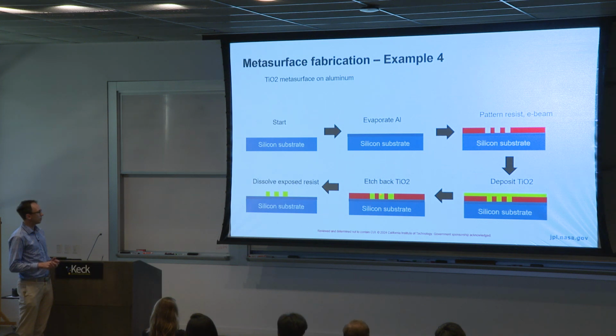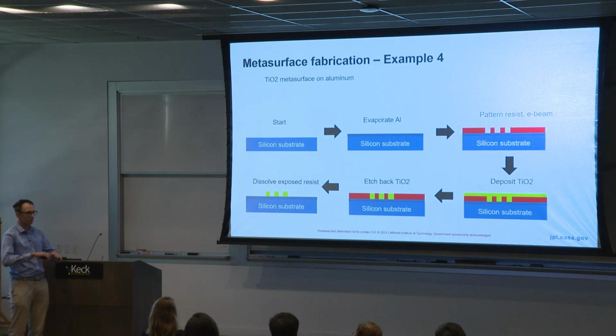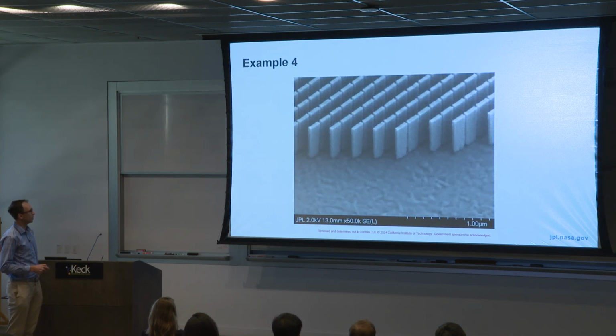And why I'm showing this example is because this is a very different type of fabrication process where the pillars themselves, so we use etching, but we don't define the metasurface itself using the etch technique. So the pillars, or the metasurface, is here completely defined by the lithography and the material deposition itself. The etching is only used to kind of expose the photoresist to release the metasurface from its resist matrix. So this has gotten fairly popular lately to utilize. And the result might look something like this, where you have titanium dioxide pillars that are fairly rectangular, and they sit on a slightly roughened surface of aluminum.